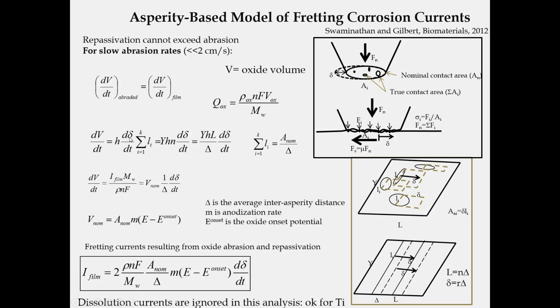The consequence of this assumption is that you can then calculate the film-based currents, again, from parameters that can be measured directly from the experiment or are from literature values. So we have a tool to tell us how much current we should expect from so much area abraded of a surface, depending on the size of the abrasion and the abrasion rate, dδ/dt.